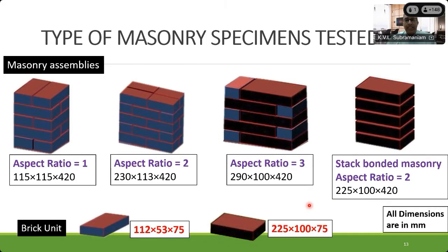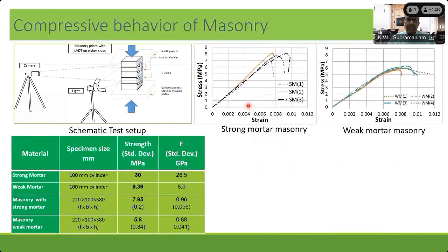So what we did to understand the failure of the brick is we made several masonry assemblies with different aspect ratios, just to understand what would happen when you vary the aspect ratios. Masonry with different arrangements of head joints and bed joints. So they made these different masonry assemblies, and then we tested them. Now, before that, what I wanted to show you is how masonry behaves in the stack bonded.